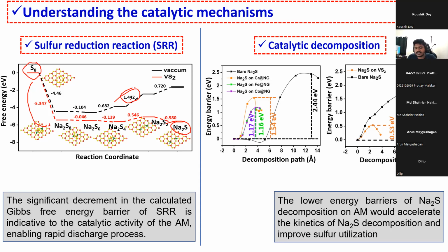In our sulfur reduction reaction process, you can see that Na2S4 to Na2S2 conversion is slower with a higher value. But when we put that on the VS2 substrate, we found that this value significantly reduced from 1.442 to 0.546. That clearly means that if you have a VS2 material, then it can easily convert the polysulfides without any hassle. The conversion rate of polysulfides with this substrate is very high. And even this Na2S2 to Na2S conversion is around 0.720. It's also endothermic in nature, but when we put that on our VS2 substrate, then it can easily convert the polysulfide and the reaction is exothermic in nature.